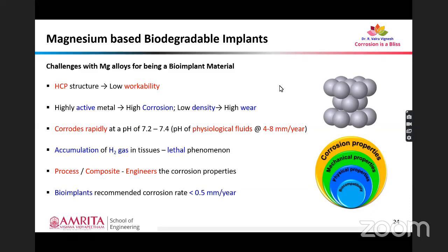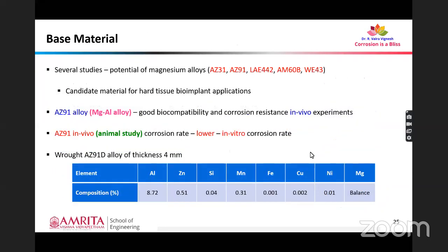Generally, the recommended corrosion rate for bioimplants is less than 0.5 mm per year. So if we are able to achieve this corrosion rate of less than 0.5 mm per year, that could be considered an effective biodegradable implant. I hope we are clear until this concept. Then we have chosen magnesium alloy AZ91 as our base material in this study.